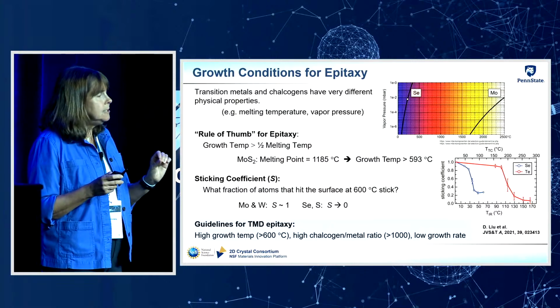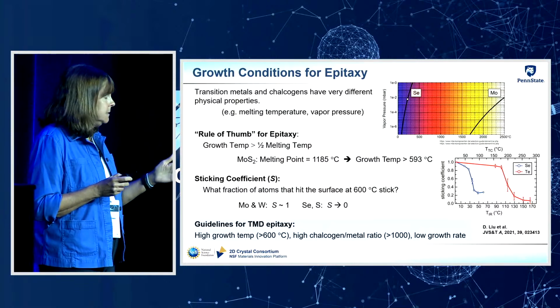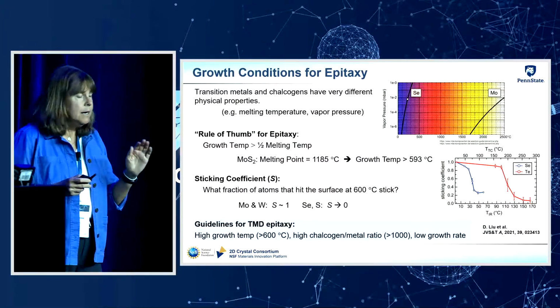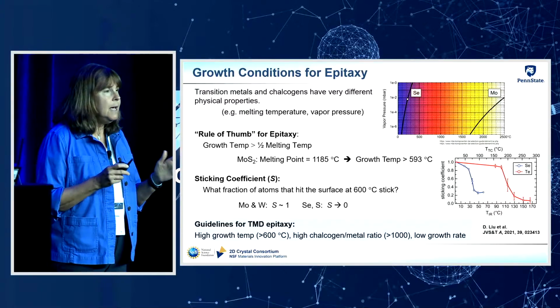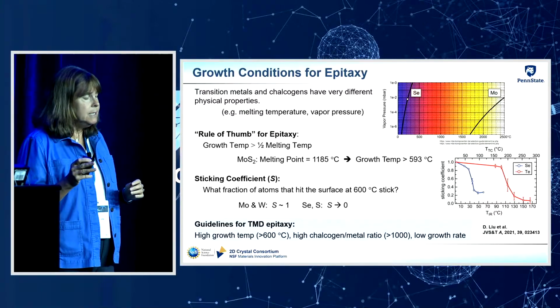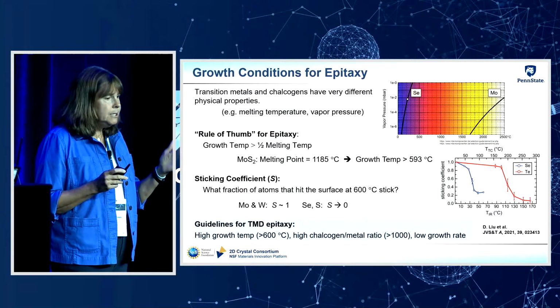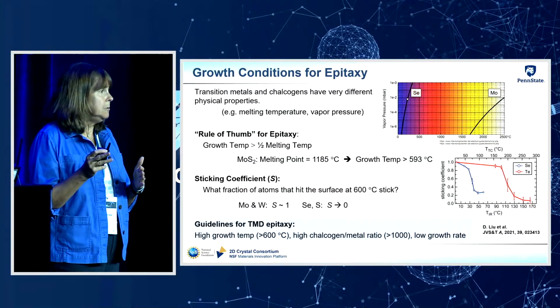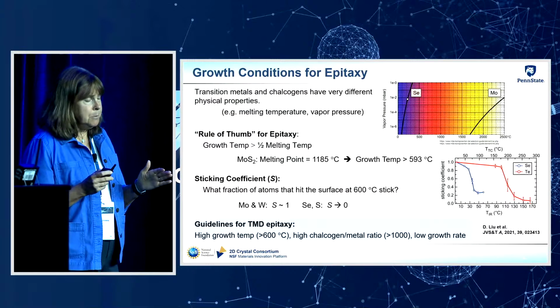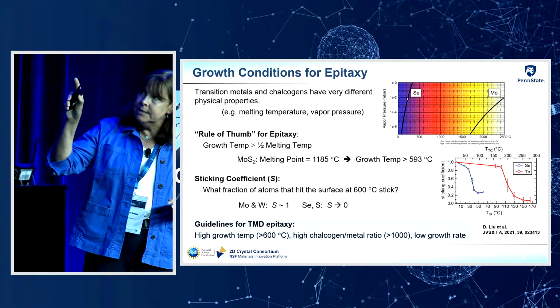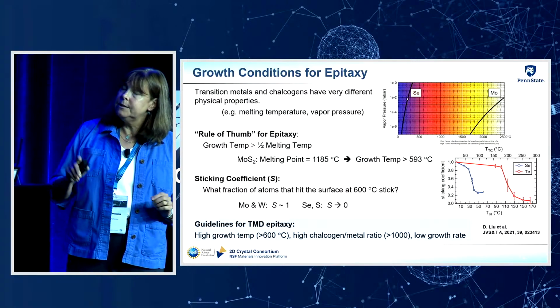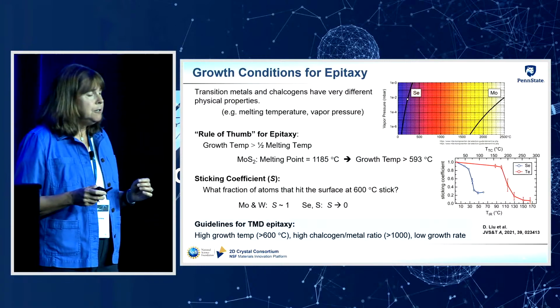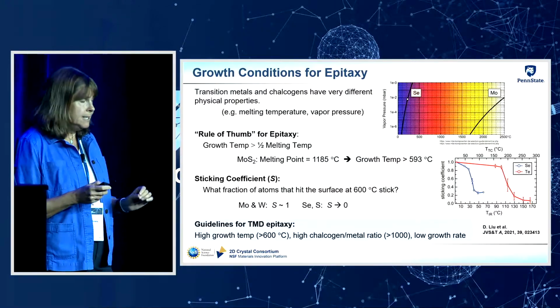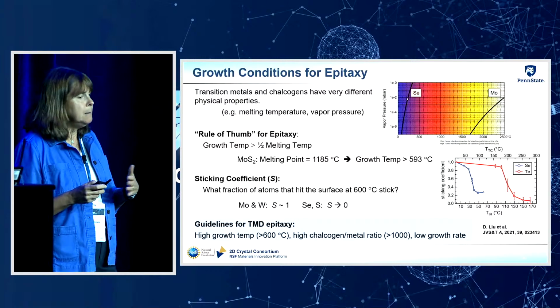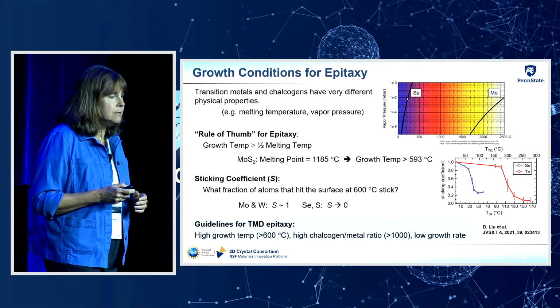The first is just the physical properties of the elements that comprise the film. All right, so we have the transition metals. We have things like molybdenum and tungsten. Those are materials that have high melting temperatures, right? They have very low vapor pressure. As you can see on the figure at the top right, the vapor pressure of molybdenum is very, very small, unless you get to very high temperatures in excess of about 2000 degrees C.